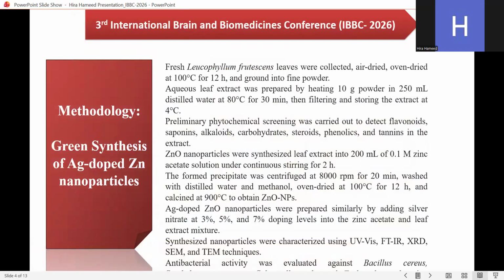Here is the methodology of my research. I took fresh Leucophyllum frutescens leaves, air dried, oven dried them at 100 degrees centigrade for 12 hours, and ground them into a fine powder. Then I prepared aqueous leaf extract.